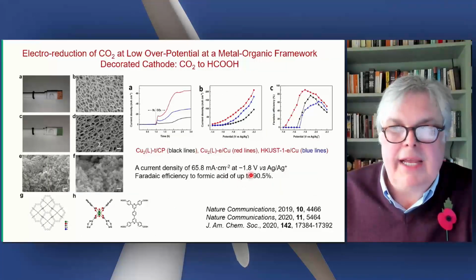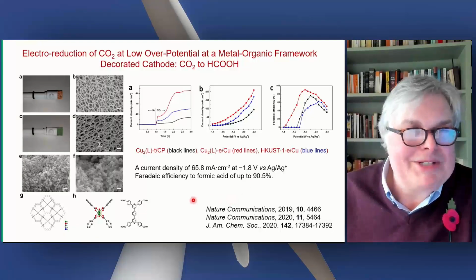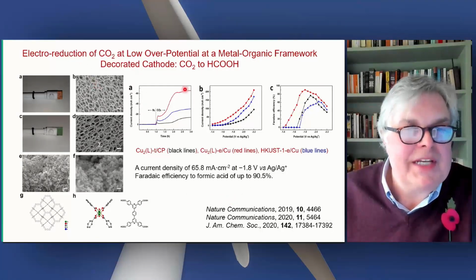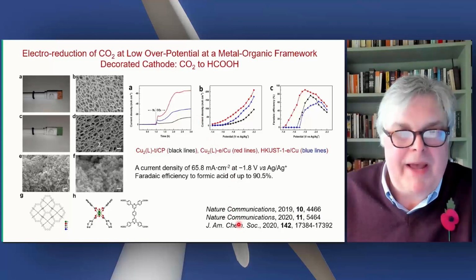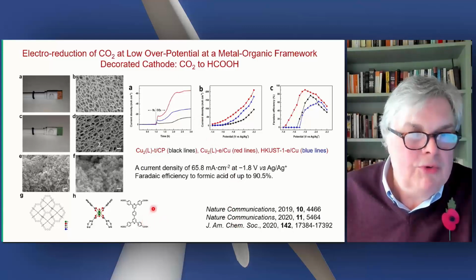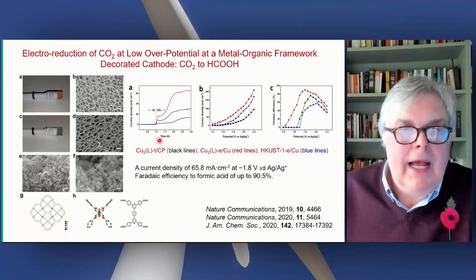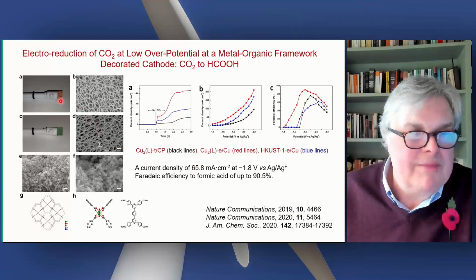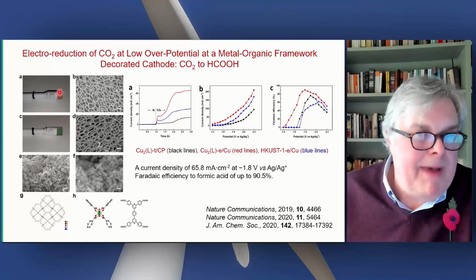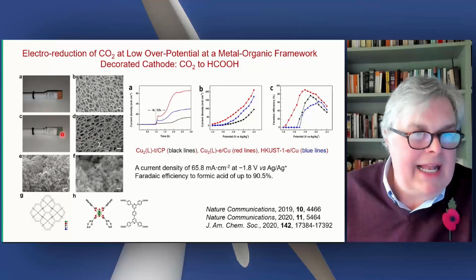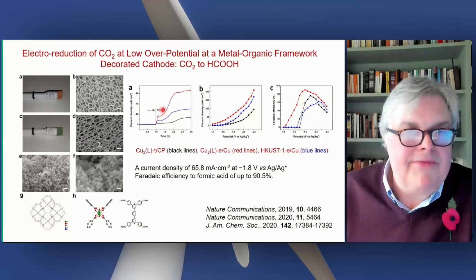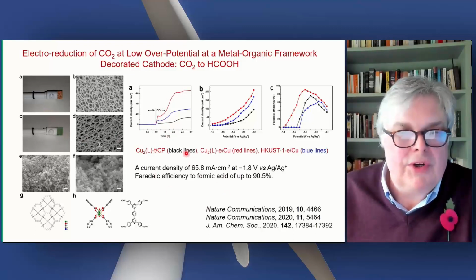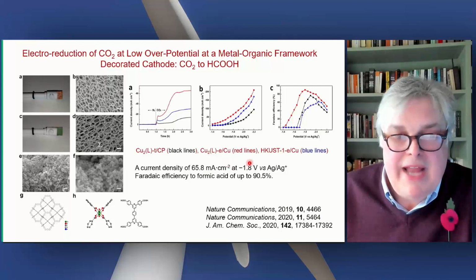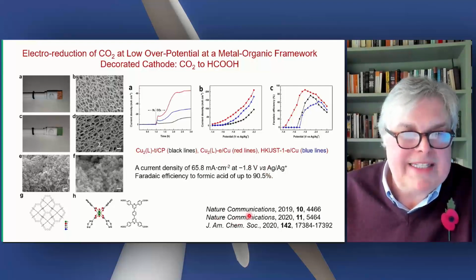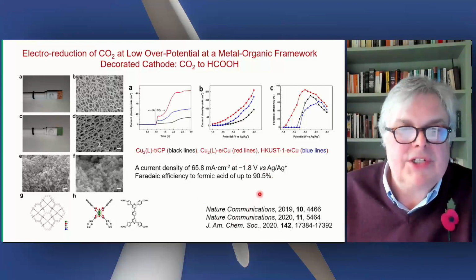And the final slide, apart from the next ones, is electroreduction of CO2. We've published a number of papers recently on CO2 reduction to formic acid. I emphasize this in terms of electrosynthesizing. This is bare copper mesh. There is the MOF on the mesh, and you can use this electrocatalytically. It's very effective for the reduction of CO2. The potential, of course, is too negative at the moment, but the MOF itself is stable under these conditions